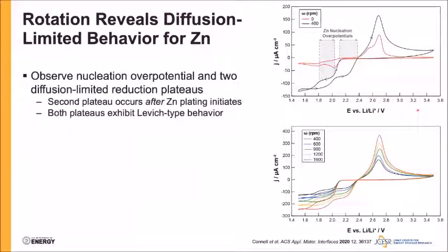So the really interesting thing is that as we start rotating in these mixed TFSI chloride electrodes, we see two diffusion limited plateaus in the voltammetry. And this second diffusion limited plateau occurs after zinc plating initiates. What appears to be the case is that there are two separate nucleation overpotential events as you go to more and more negative potentials, corresponding to two separate initiations of zinc deposition.